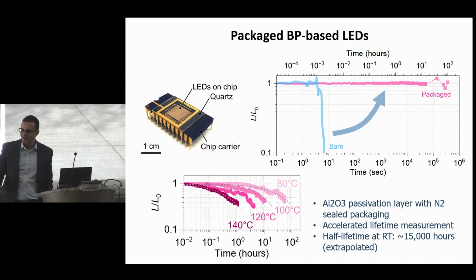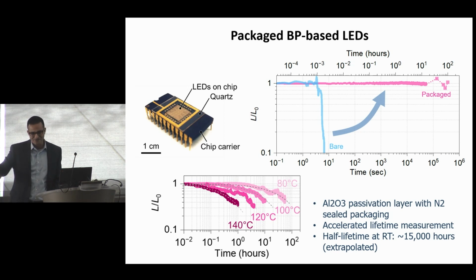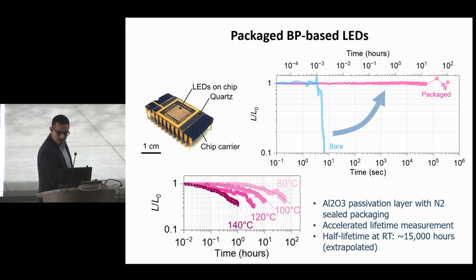Now, for the case of LEDs, what we did was we packaged them properly, and the way we did the packaging is what people had done for black phosphorus transistors before. And for transistors, I don't think black phosphorus makes sense just because the band gap is wrong, unless you go to monolayer, but for monolayer, it's very, very unstable. And so for the black phosphorus, we just passivated with aluminum oxide. This is ALD oxide. And we then put it in a chip carrier, and we basically sealed it in epoxy. And then we measured the operation lifetime. So we continuously operated the device at a pretty high intensity. I forgot the intensity, it's in the paper, but it's higher intensity than what you can buy today for mid-IR LEDs. And we are running it for, you can see how many hours, over 100 hours.